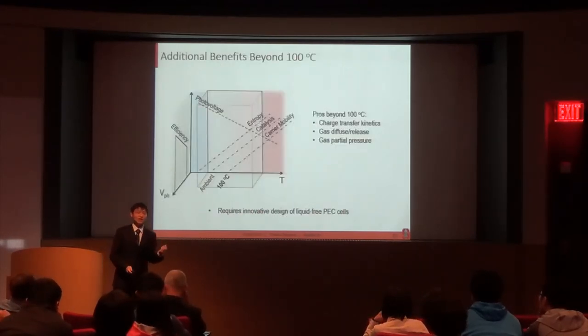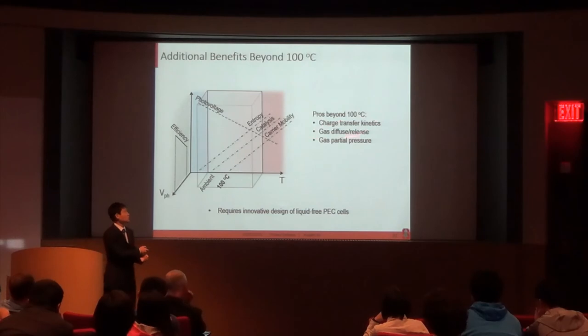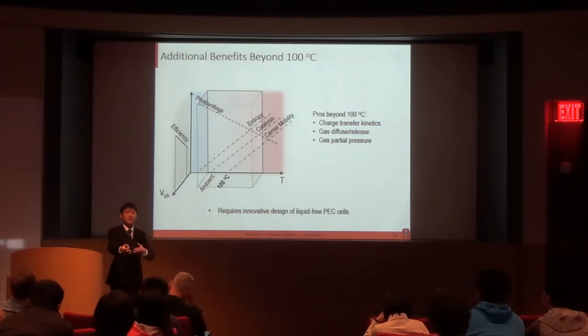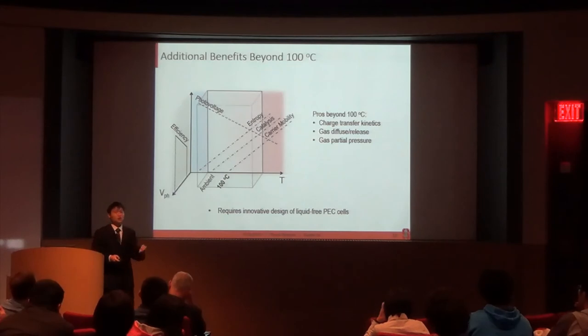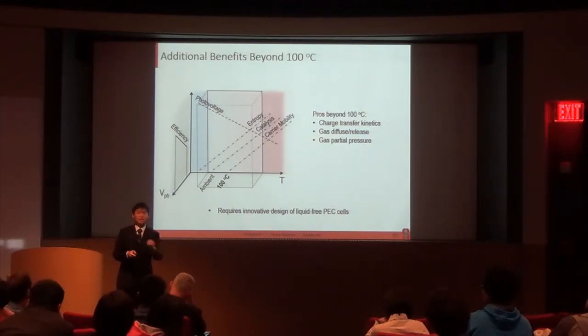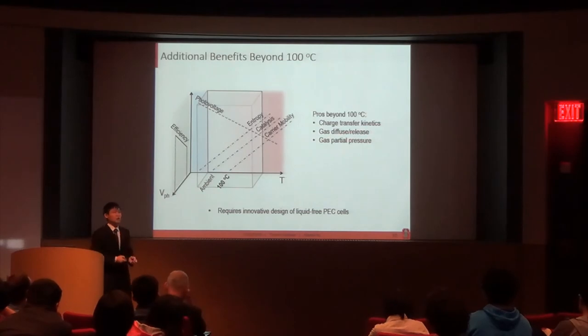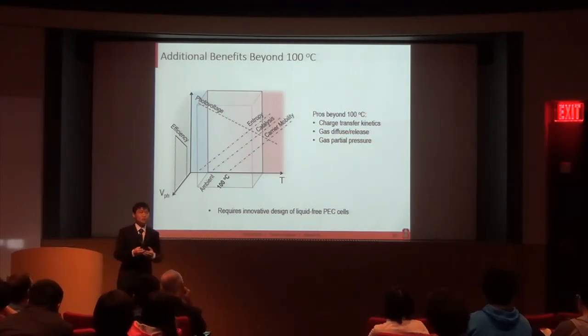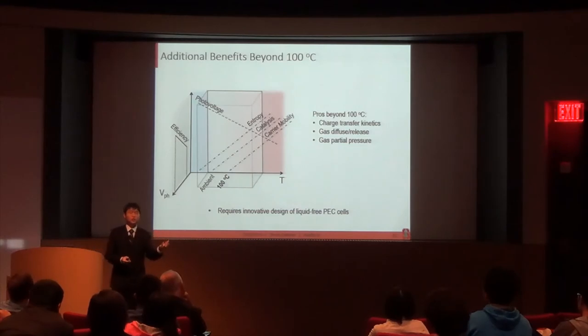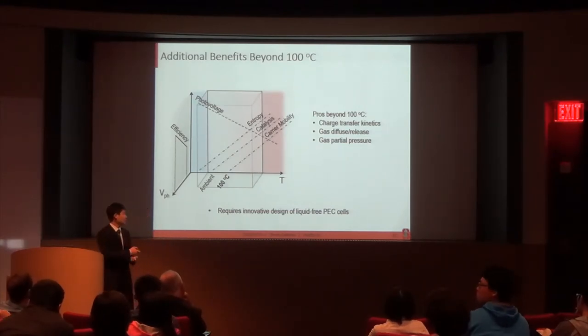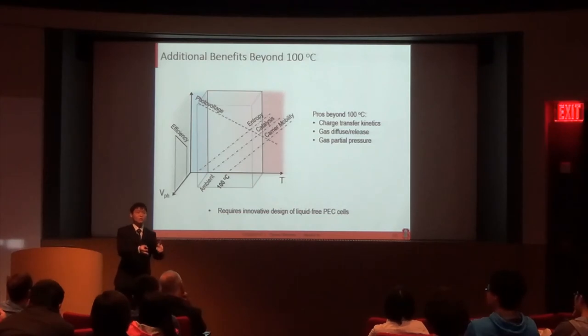Actually, in spite of this challenge, there's additional benefits to going beyond 100 degrees Celsius, such as the charge transfer kinetics becomes even faster. This not only includes the reaction kinetics, but any kinetic charge transfer across interfaces. The gas diffusion and release becomes faster in the gas phase as compared to the liquid phase. And we also have easier control in the gas partial pressure, which is another knob to tune for reaction kinetics. So that requires us to innovatively design a liquid-free PEC cell that could work under temperatures significantly beyond 100 degrees Celsius and under concentrated light.